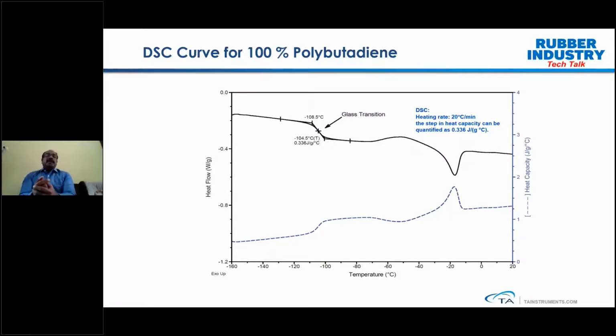When you run 100% polybutadiene, we can clearly see a glass transition temperature at around -100. In DSC you have the ability to go to negative temperatures. In this particular DSC, the run is performed with the help of liquid nitrogen. We started from -160 degrees centigrade, and we can see a clear step change because this is 100% polybutadiene. As you heat further, the amorphous material crystallizes, and as you heat further, you can see the endotherm due to melting, and the same is reflected in the heat capacity signal. You can see the heat capacity increasing above the glass transition temperature.